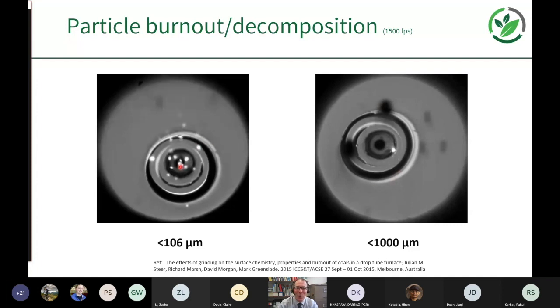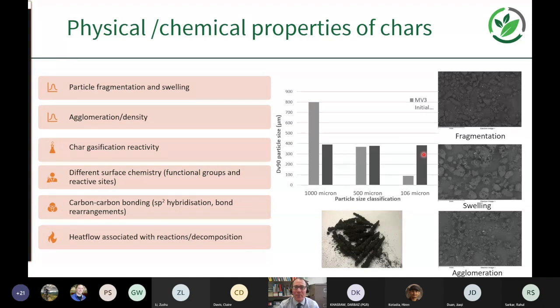On the left-hand side, you've got a more regular, symmetrical propagation and combustion of materials. And then on the right-hand side, this granulated injection, higher particle sizes, tends to be more fragmented. You see this particle fragmentation. So what I'm suggesting is that when coals are injected, they behave very differently. They burn out very differently, but they also produce, because they don't completely burn out,